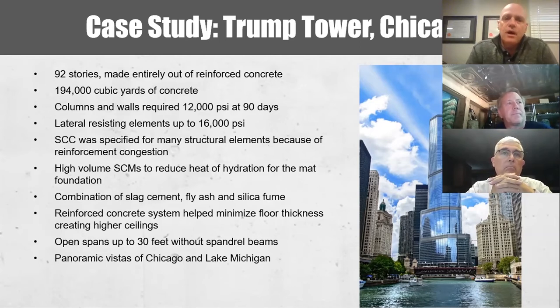Now, self-consolidating concrete was specified for most of the project because of high reinforcement congestion, and high volumes of SCMs were used to reduce heat of hydration. It used a lot of ternary blends and in some cases quaternary blends. In other words, Portland cement, slag cement, fly ash, and silica fume to meet the requirements. And the whole idea here, obviously a high-end residential building, was 30-foot spans without spandrel beams. And if you've ever seen the location of Trump Tower in Chicago, there are beautiful vistas of the lake along the Chicago River.